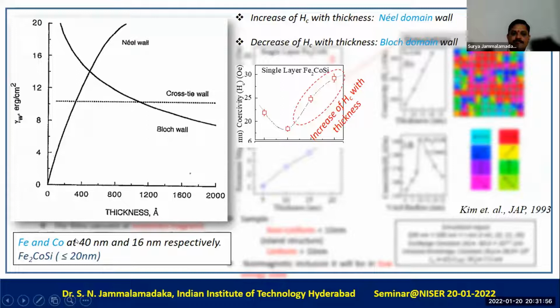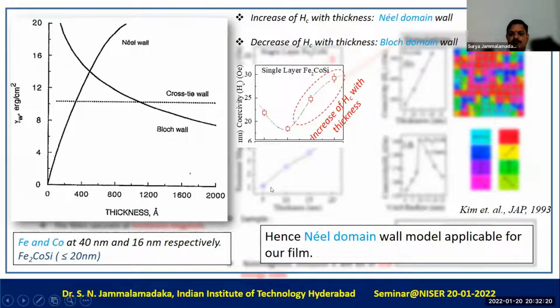Okay, so the increase of the coercivity in a thin film leads to the Néel domain wall. And if the coercivity decreases as you increase the thickness, that can lead to the Bloch domain wall. So again, further to confirm, for iron and cobalt, if you want to have Néel domain walls in the film, the thickness must be less than 40 nanometers in the case of iron, and in the case of cobalt, it must be 16 nanometers. So as we are dealing with a system of 5 nanometers, we do believe that Néel domain walls exist in our sample. Hence the Néel domain wall model is applicable for our film.